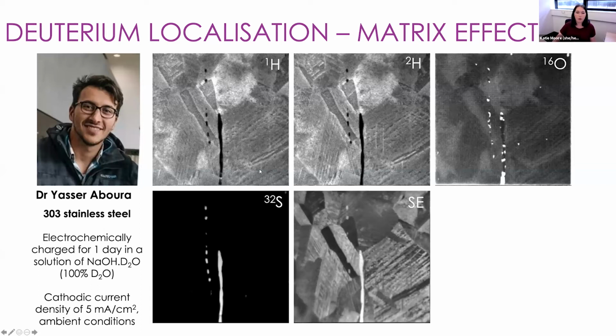Here, what Yasser started working on first was a 303 stainless steel. The reason we chose this alloy was because if you read the literature, it's very clear that manganese sulfides are supposed to be the location where hydrogen is trapped. So we thought, great, that will give us a very clear feature we can look at in the NanoSIMS. They're easy to find, and we should be able to see deuterium localized to these manganese sulfides, and we'd get a sort of benchmark of what we can and can't do from that.